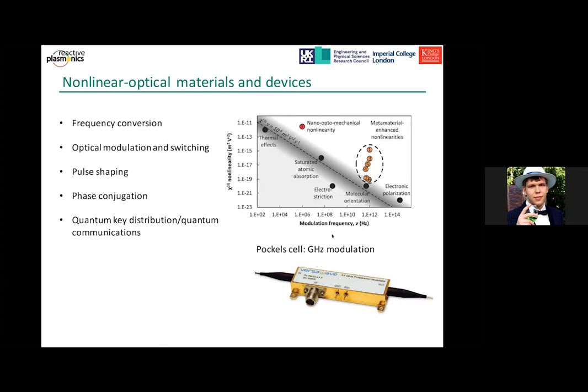As you can see, the search for alternative nonlinear materials is continuing. And as you can see from the graph here, which lists the third order nonlinear susceptibility, which is relevant for optical modulation and switching, most of the standard materials follow the same trend along this graph. And some non-parametric metamaterial nonlinearities here can actually go away from the common trend, allowing to explore different regions in the parameter space. So it gives additional incentive into studying this effect in these materials.